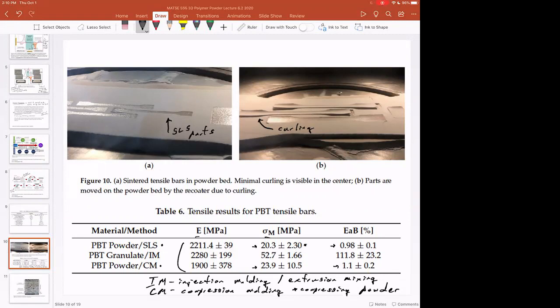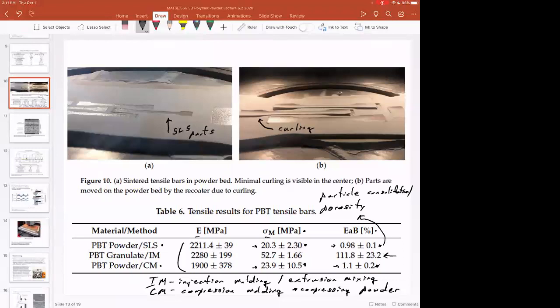And so all of these values are because of particle consolidation or porosity leads to lower strength at failure and lower elongation at break versus injection molding. And so as we discussed last time, this is the real flaw of SLS, trying to get all that powder to stick together without any defects. Usually the parts have reasonable moduli values, but their strength at failure and their elongation at break are lower because of the consolidation of the powder. So that's something to think about as you think about how to use these processes.